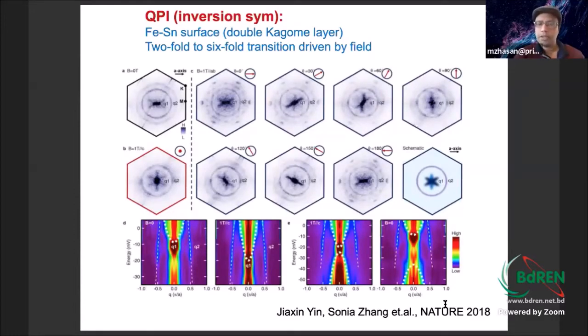If you have nematic order, then that's a clear sign of strong correlation. For example, in this iron compound, we clearly see, even though the crystal structure, the surface, has a hexagonal structure, the electronic structure is twofold. So clearly there is nematicity. Not only that, of course, there are many systems that are nematically ordered, but what is new or unprecedented in this compound, in all of condensed matter physics, is that here, using a magnetic field, you can dial the nematic order direction. I don't know of any other system that can do that. So in other words, you have control over nematicity.